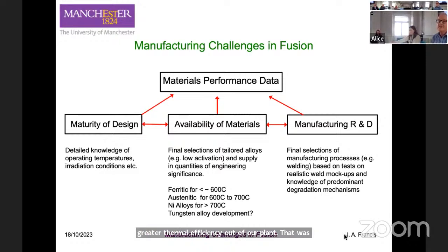That was a 25-year program to increase by 90 degrees, involving creep testing, where you've got components going into service for 25, 30 years. If you don't test for a year in a creep test, industry would often say the tests aren't credible. If you have to accelerate to do a test in 2 months, you're heating the material up, changing the microstructure, changing the deformation mechanism. You're not testing in a regime that is relevant to service.